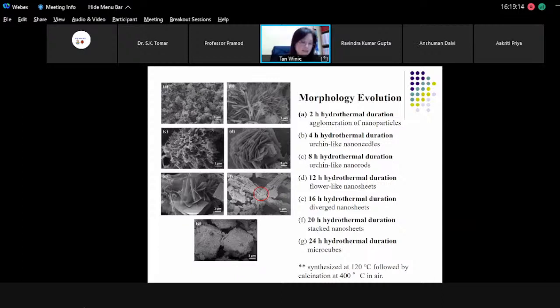You can see that at 2 hours, we have agglomeration of nanoparticles. At 4 hours, we have the urchin-like structure, which looks like nano needles. When we increase the hydrothermal duration from 4 to 8 hours, the nano needles develop into nanorods, but the nanorods still maintain the urchin-like structure. So we increase the duration to 12 hours. Now the iron cobaltite evolves from urchin-like nanorods into the flower-like nanosheet structure.